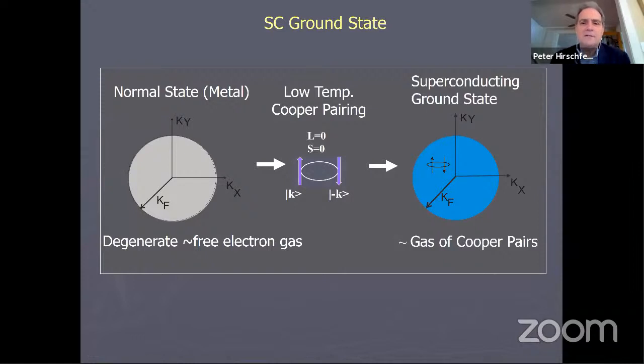Okay, the standard picture from any textbook of the superconductor is you take a normal metal with states at low temperatures filled up to the top of the Fermi sea, so that's the Fermi sphere here. You add a weak attractive interaction between opposite spin and opposite momenta particles in the relative orbital angular momentum zero and total spin zero channel. And what you get is bound pairs, which are coherent. This gas of Cooper pairs is the superconducting ground state.